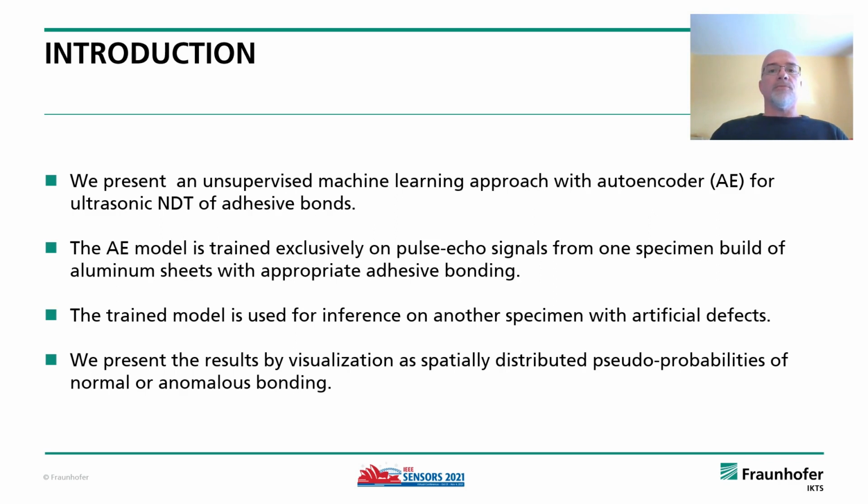The resulting pseudo-probabilities indicating anomalies are visualized and presented along to the C-scan of the same specimen. As a result, we achieved improved representation of the defects, providing a possibility of their automatic and reliable detection.